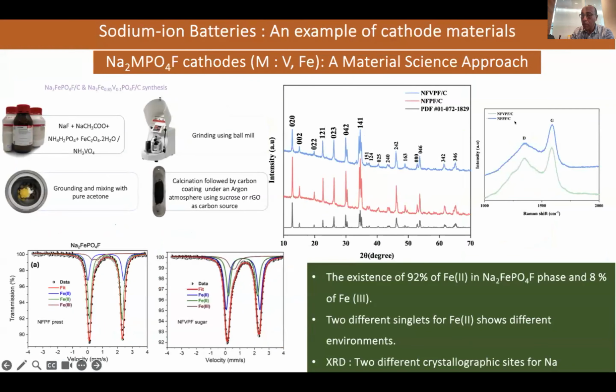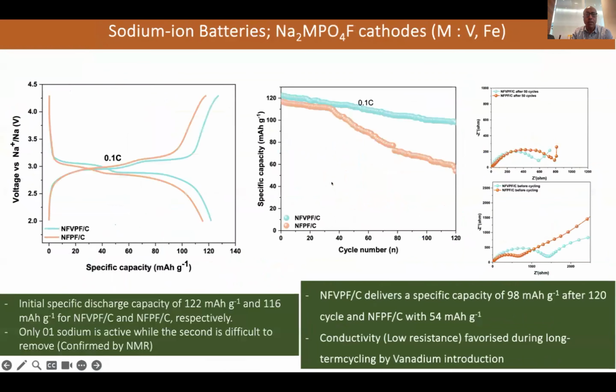We have this carbon existing in the structure. This means that we have good conductivity, more power. We are using techniques from solid-state chemistry to be sure that we have iron 2+ in the structure. And then when charging and discharging, you see that we have a good reversibility of the process, and we have this phenomenon. And to understand now, once again, we have to use our expertise in solid-state chemistry to understand why we have this discharge here when putting vanadium, and we explain it by using impedance.